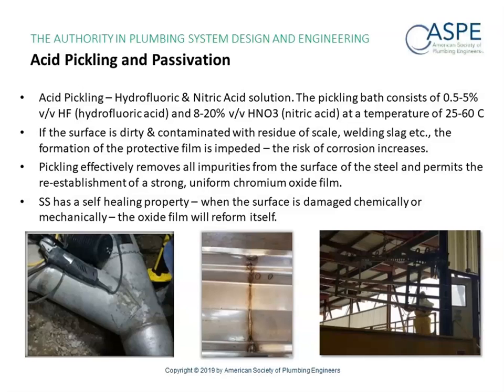So the acid pickling process removes all the impurities from the surface of the steel and helps form that chromium oxide film again. We know that stainless steel has a self-healing property, so when the surface is damaged chemically or mechanically, eventually the oxide film will reform itself if it has time to do so without being further corroded.